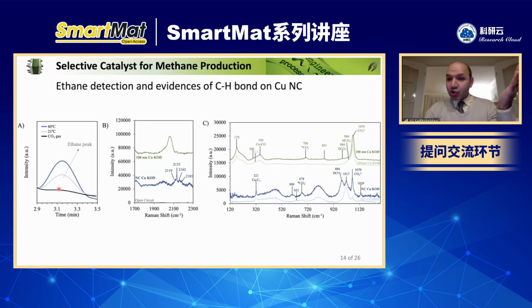But then that's a peak. It shows that we have ethane in fact. But then we increase the temperature to 80 degrees. So we expected that we should observe more ethane, and we observed that. So it's kind of supporting the idea that the ethane is absorbed there, and by increasing the temperature, you can help it to be desorbed.